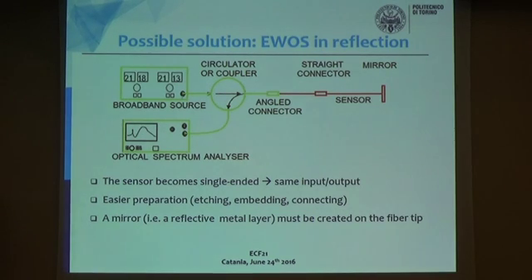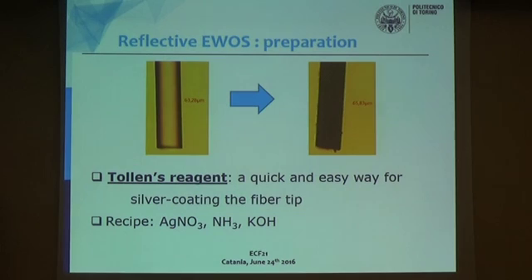And the nice feature is the easy way we found to produce this mirror at the fiber tip. You could normally use some techniques such as metal sputtering, which work very well, but they are expensive and difficult to implement. We found this simple chemical reaction that is called Tollens' reagent. It's based on silver nitrate, potassium hydroxide, and ammonia. And with a simple recipe, it's possible to deposit silver on the fiber tip. You must just cleave the fiber very precisely at the fiber tip, and it's possible to get a nice reflection from this fiber. So we basically made this new kind of sensor.